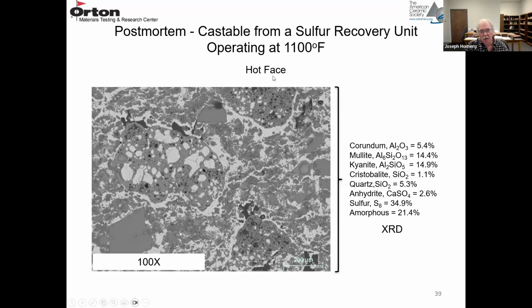So if we do an X-ray diffraction at the hot face, it's about 5% alumina, almost 15% mullite, and we pick up the kyanite again, about 15%. So the temperature was not hot enough to convert kyanite to mullite and cristobalite. We see again some residual quartz. That's probably in the kyanite. And we have some calcium sulfate and a great deal of amorphous material plus the elemental sulfur.